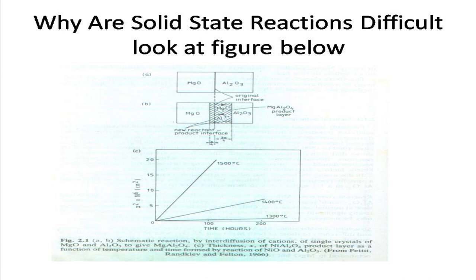Part B tells you the situation of the reaction after a certain number of hours at a temperature of around 1500 degrees centigrade. Now, what do you see in this? The interface that was existing in the original diagram has now shifted towards both the right hand side and the left hand side. The shift on the left hand side is smaller, and on the right hand side is much bigger. That means the formation of MgAl2O4 is taking place on both sides, but the rate of its formation on the two sides is different. I shall explain later why on one side it is proceeding fast and on the other side it is proceeding slow.